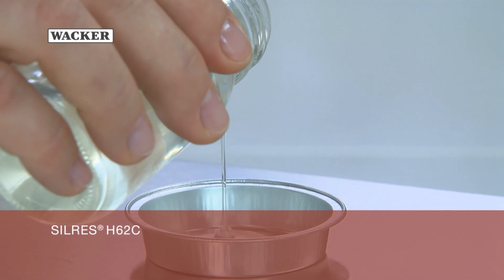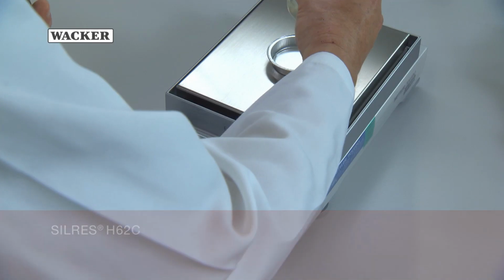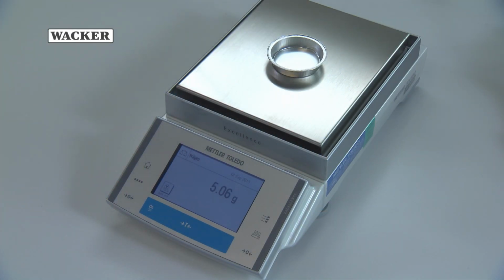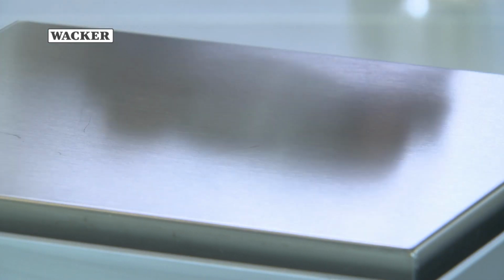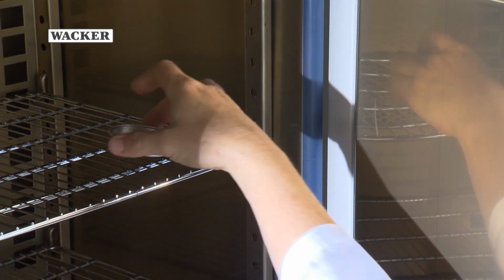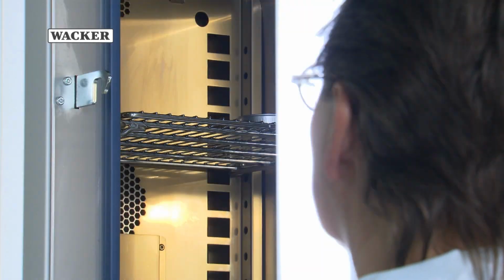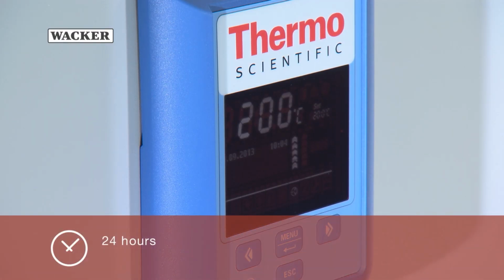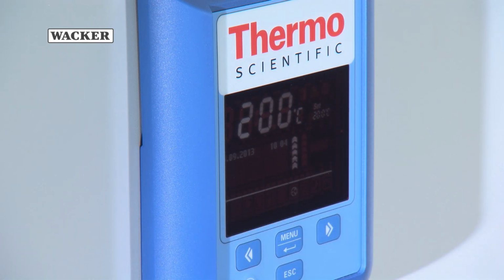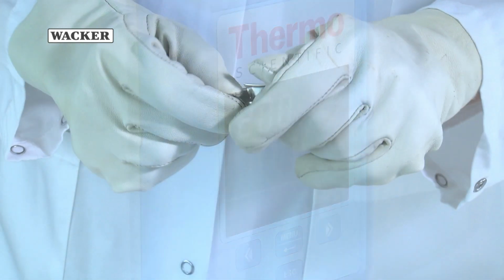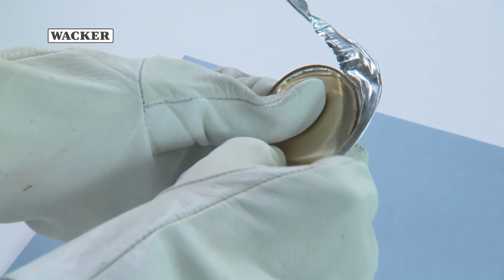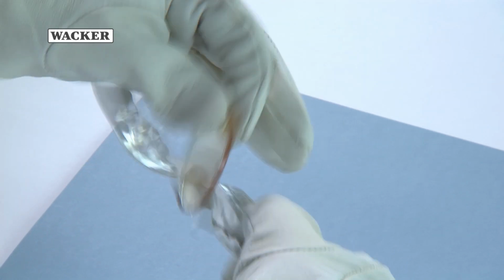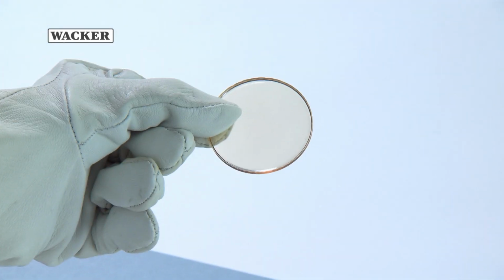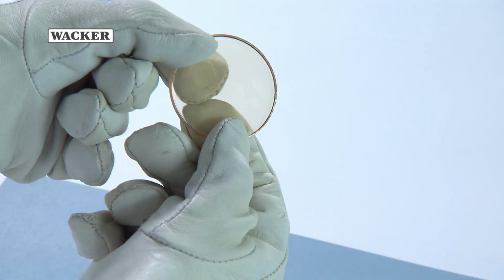SILRES H62 C is a liquid, solvent-free silicone resin that already contains a sufficient amount of a platinum catalyst. SILRES H62 C cures from a temperature of roughly 160 degrees Celsius, although temperatures of 200 degrees or higher are preferred. Unlike standard silicone resins, this does not release any byproduct, making it particularly suitable for compact encapsulation or for electric motor impregnation. The hardness of the finished cured rubber is roughly 60 Shore-D.